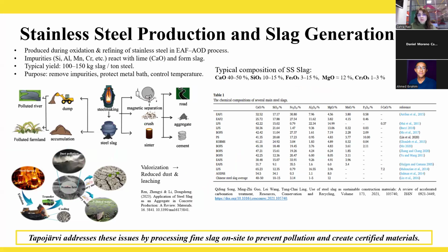Stainless steel production at Acerinox generates around 100 to 150 kilograms of slag per ton of steel, and the fine fraction represents a considerable amount of that. Chemically, it's composed mainly of calcium oxide, silica, magnesium oxide, and minor amounts of iron and chromium oxides. Untreated, these slags can cause environmental problems such as leaching of heavy metals or dust generation. However, once processed, the material becomes inert, dense, and non-leaching, meaning it can safely be reused in road construction, asphalt, or concrete applications. This approach supports the European Circular Economy Action Plan and UN Sustainable Development Goals 9 and 12, reducing landfill use and raw materials extraction.